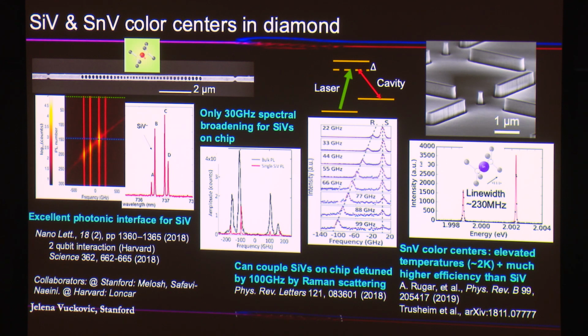And recently we started looking into alternatives to silicon vacancy color centers, in particular tin vacancy, which has exactly the same energy level structure as silicon vacancy, and also looks the same in geometry. It's just an extra silicon or tin atom between two vacancies of carbon atoms in a diamond lattice. It's also inversion symmetric, immune to first order electric field perturbations, and so on. So it's more immune to environment than the nitrogen vacancy center.